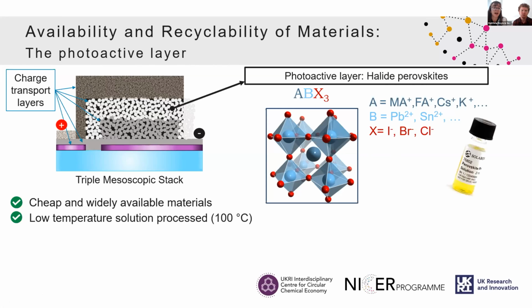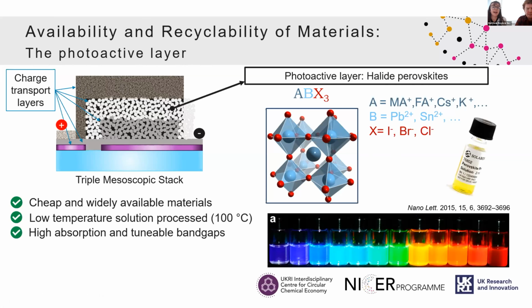They have the advantage that they are easily processable at low temperatures, because they can get dissolved in a solvent, and then you can just pretty much create an ink, and then you can print these inks and it dries at 100 degrees. So low energy processing, as we ideally wanted. They have the peculiarity that depending on the elements that you choose to form them, you can change the color, which means you can absorb into different wavelengths. And that allows you to do interesting things, like, for example, getting different colored cells and working with different absorbers as well, so that you can create a tandem, for example.